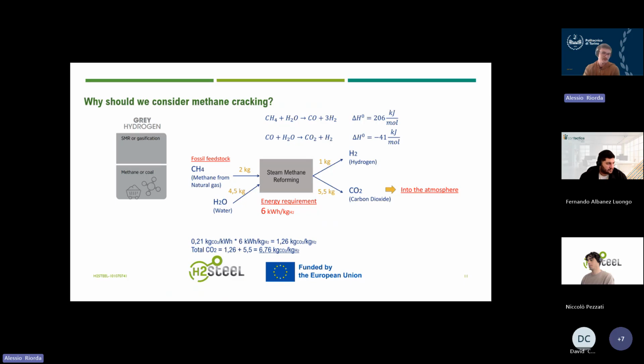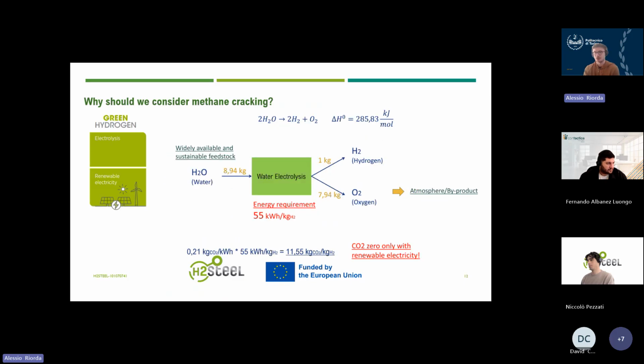That goes into the atmosphere. One solution that we can see today is water electrolysis. That is, of course, an interesting solution, because we are starting from a non-carbon feedstock, and then you can obtain 1 kilogram of hydrogen from just 9 more or less kilograms of water. It will require a lot of energy, and if this energy is not from renewables, that will lead again to the emission of CO2, a good amount of CO2, as you can see at the end of this slide.